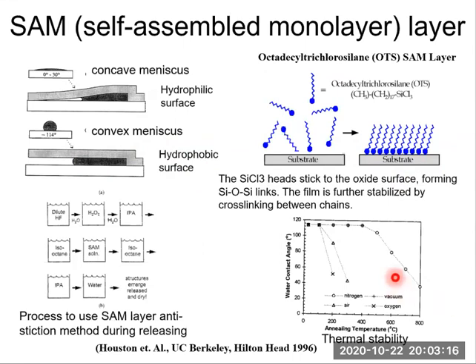This figure plots the thermal stability of the OTS assembly. The vertical axis is the water contact angle. The horizontal axis is the annealing temperature. Now we can observe that in nitrogen and vacuum, the contact angle remains constant, about 114 degrees, up to 400 Celsius. So the thermal stability is pretty good in nitrogen and vacuum. But in air and oxygen, the contact angle starts to decrease at about 100 Celsius. So we can see oxygen has a big impact on the thermal stability of OTS assembly.